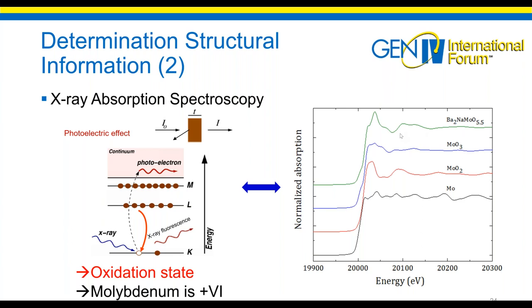And also you need some references with a different oxidation state. So here is 0, here is 4, and here 6. And thanks to these references and the measurements of our quaternary compounds, we found out that molybdenum was 6 in this structure. And so combining,